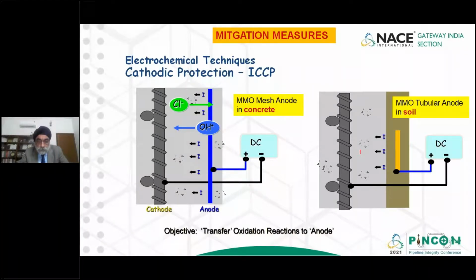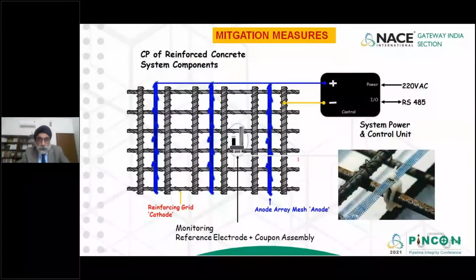Now this photograph basically shows MMO mesh anodes which have been installed in the reinforcement. The blue color are the MMO mesh anodes which are connected to the positive of the rectifier, and the negative of the rectifier is connected to the steel reinforcement. In the center, we have embedded reference electrodes, which are basically silver chloride reference electrodes, which measure the potential of the rebars.